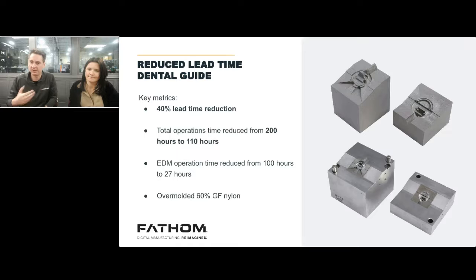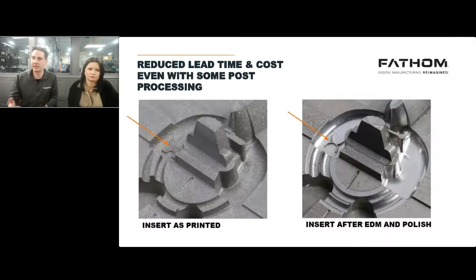There are a lot of features on this part that would require a lot of sinker EDM time. It was going to require 100 hours and a ton of different electrodes. They still did some EDM work afterwards, which I'll show you here, but they went from 100 hours of EDM down to just 27 hours. It's really important to know that you can still do all that burn work and all that finishing work. But as you can see here, they overprinted some of these features and then did one final finish burn, instead of having to burn all those features from scratch out of a block, which would have taken a lot longer with that milling and burning process. Which, of course, is the common theme today: the desire to remove and eliminate EDM is super important.